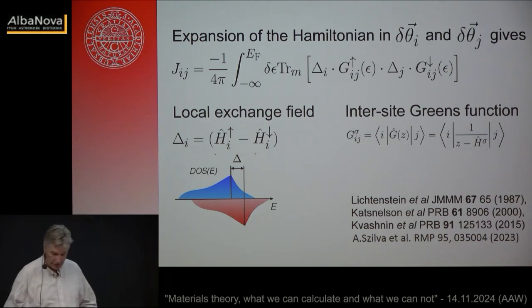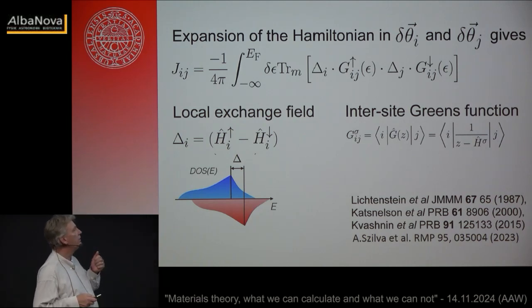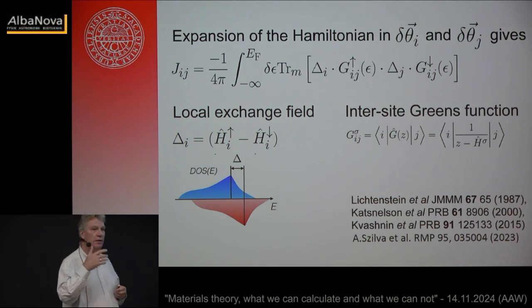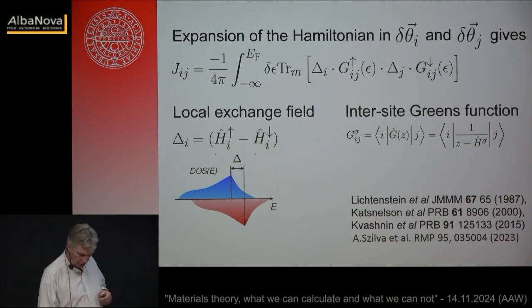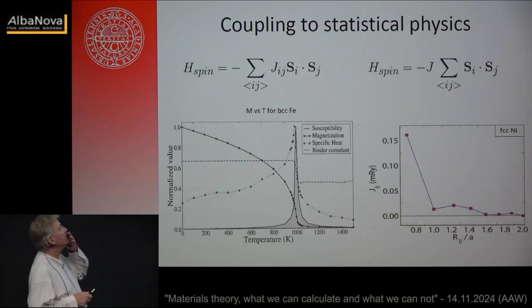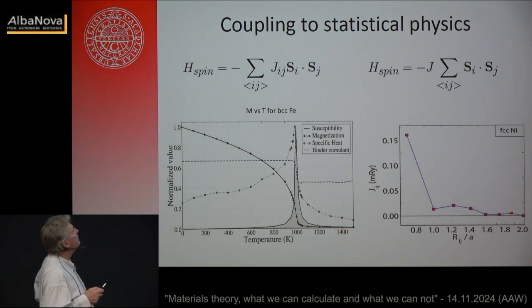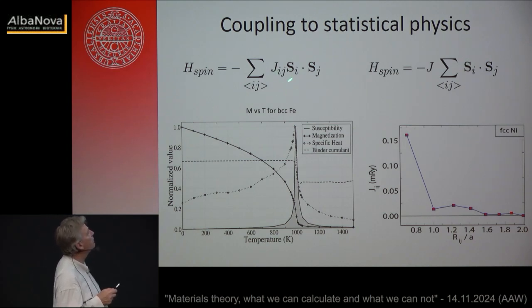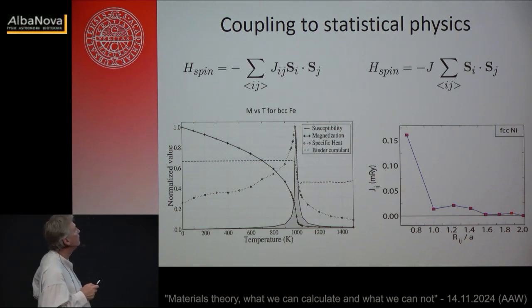And so it's a very nice way to do a multi-scale calculation, to go from one scale to another. The scale of the electrons and 1 unit cell and so on, to a much wider ranged scale. And so we and others tried this, and so we calculated of this effective spin Hamiltonian everything, the interaction, the value of the magnetic moments. That was this diagram I showed a little while ago. And then you can subject this to Monte Carlo simulations and calculate magnetization versus temperature. That's shown here again for BCC iron.